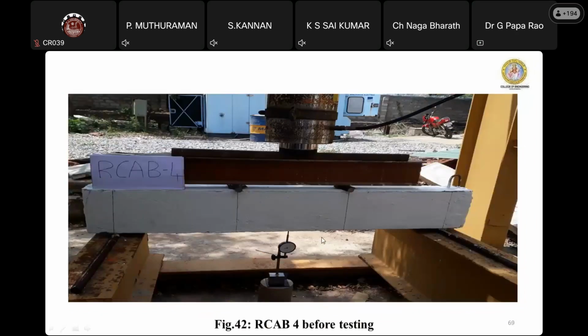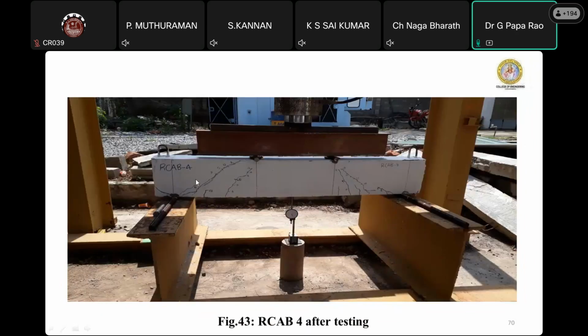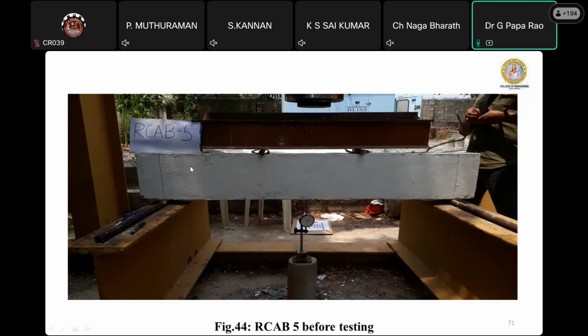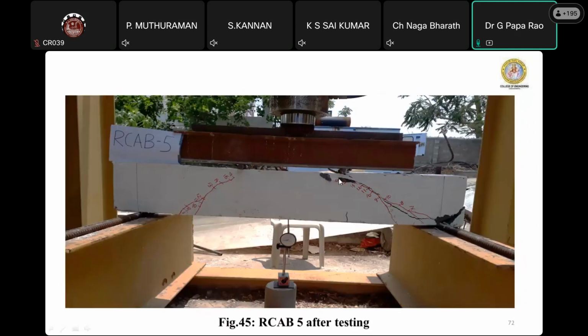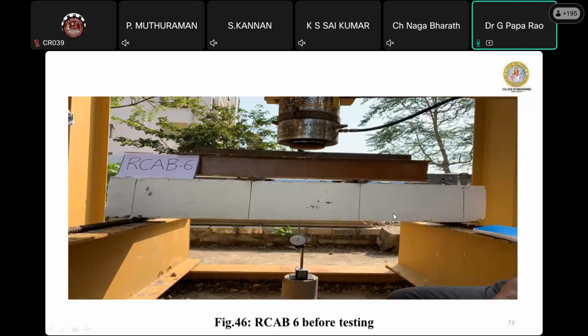And this is RCAB4, so 50% natural coarse aggregate, 50% recycled coarse aggregate. Again, you can observe the mode of failure. This is again shear failure. RCAB5, 75% recycled coarse aggregate, 25% natural coarse aggregate. Again, the mode of failure is shear.